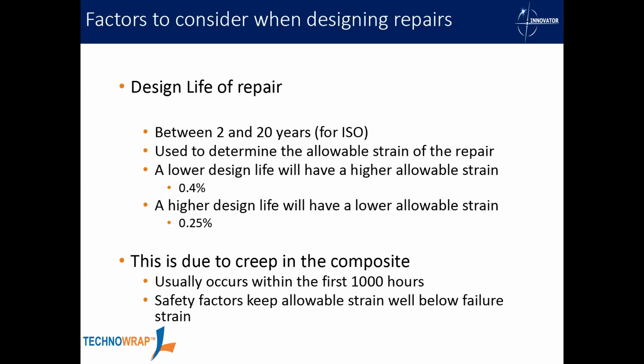And what this comes down to is the actual strain within the composite. So the fiberglass will probably have a failure strain of about 2.4%, maybe a carbon of about 1.5 to 2%. And what we do is we derate the allowable strain based on design life. So a short-term repair, a 2-year repair for example, would have a higher allowable strain than a longer-term repair, which would have a lower allowable strain. So simply, we're putting a bigger safety factor onto longer-term repairs. And the reason for that is creep in the composite.